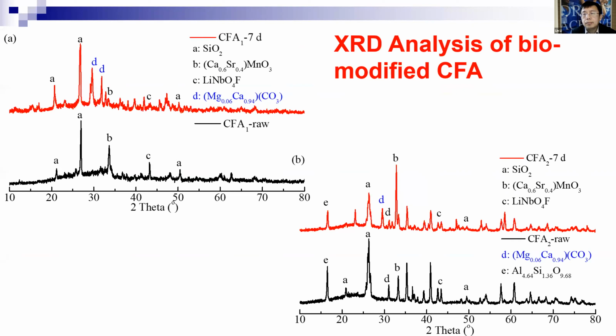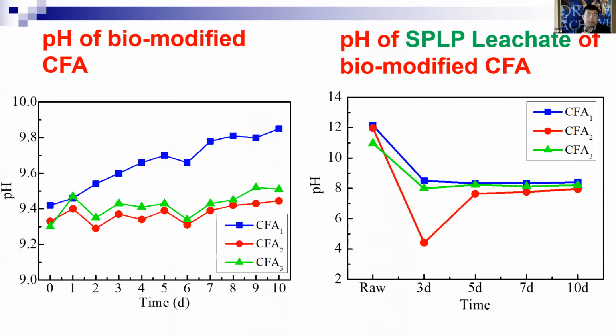You can see the blue color showing the new type of carbonate mineral forms. We also looked at the pH. The pH of the bio-modified ash is about 9.4, 9.5, and as time goes on, the pH increases. But when we look at the leaching pH for the SPLP leaching, the pH is quickly stabilized at about 8.